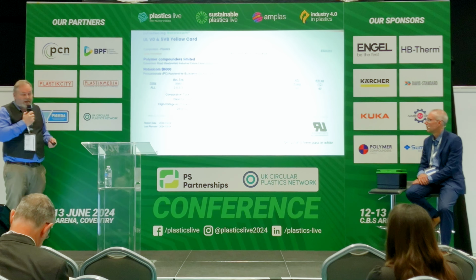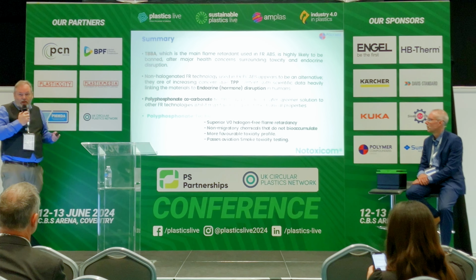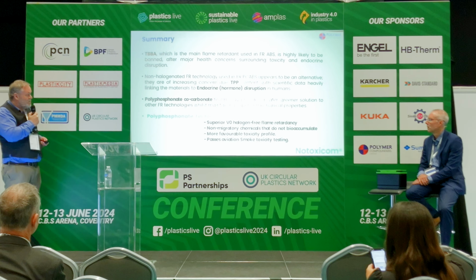So to summarise, TBBA is highly likely to be removed from the market after major health concerns. It went on the Substances of Very High Concern list in January 2023, and it will be very quickly removed, and that basically is the end of FR ABS. FR PC ABS contains liquid flame retardants that contain triphenylphosphate, which, as Richard showed you, is also a product which is going to be under the same type of spotlight as the halogens are at the moment. Our polyphosphonate carbonate technology provides a safer solution, maintaining mechanical properties, and as you saw in a few cases, superior mechanical properties. And what Richard has at his side to show that the product is real is a battery casing made in green colour and in black colour from our Notoxicom product.